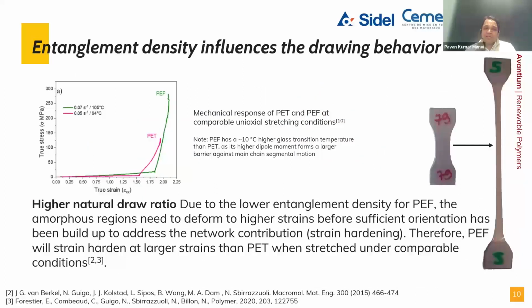Then we look also at how it can be practically implemented. Because of this phenomenon which we studied on the previous slides, we can see that due to the lower chain entanglement density of PEF, PEF can be drawn more than PET. You can see in the curve that the green curve is for PEF and the red one is for PET. If we see where the strain induced crystallization, or in other words strain hardening, starts, it starts under similar conditions but at a higher strain in comparison to PET. That means PEF allows higher draw rates or drawing in comparison to PET before the strain hardening starts, which is related again to the high orientation level of the polymer chains, and which can result in better mechanical properties than PET.